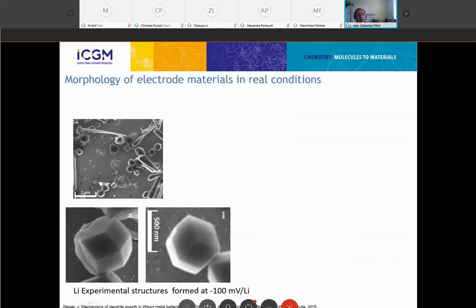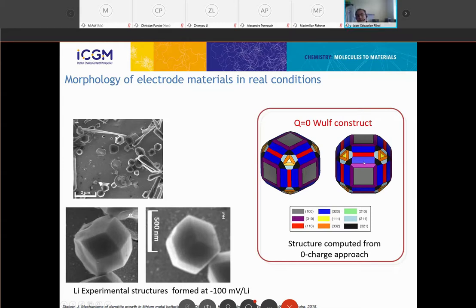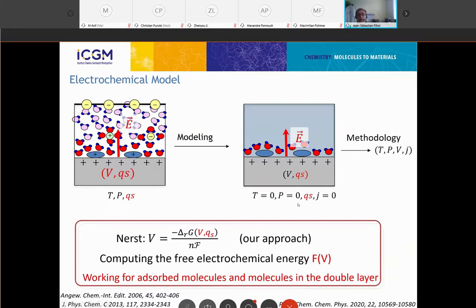As an example, I'm going to talk about the simplest system, lithium reduction and the formation of nanocrystallites. If you compare the shape of the nanocrystallites to what you get using only the surface energy from DFT calculation, you get very, very different structures. So the classical approach using zero charge can be very wrong in getting proper energetics for the interfaces. What you need is more complex modeling that includes the surface charge, the electric field, and eventually explicit and implicit solvation of your interface.